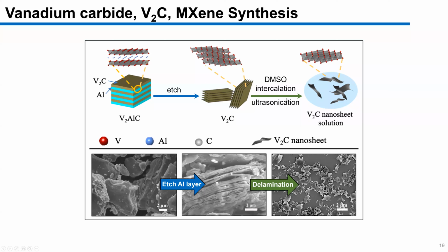And then after that, you apply some organic solvent to expand the spacing in between the layers. And then you gently sonicate and you can essentially form nanosheets, as opposed to these sandwich or accordion-like structures, in solution.